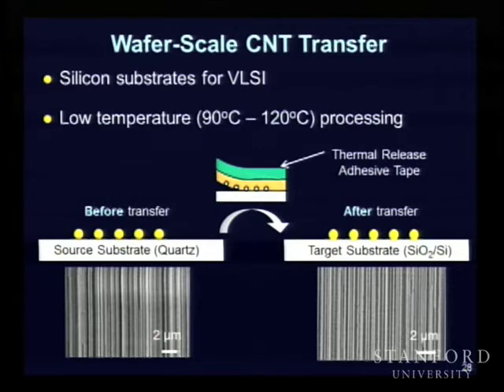Now life is not that simple because you have to worry about a few things, and that's exactly what one of the undergrad students in our lab was able to achieve in his Nano Letters paper. By doing this transfer in a very clever way, he could linearly increase the density of the carbon nanotubes on the destination substrate. Nobody has said that you have to transfer these carbon nanotubes only on the same layer.